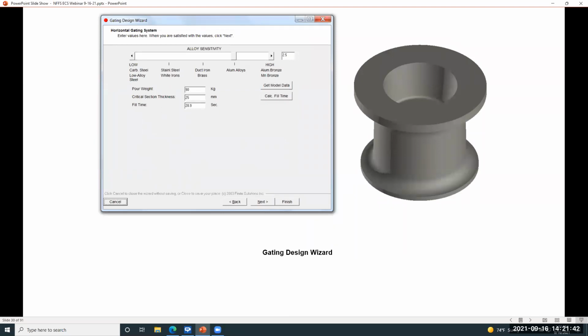In the same way, we can use the gating design wizard, essentially an electronic worksheet where we go through, the system will pull the weight information out of the model. We select the type of alloy we're working with, and we enter what's called the critical section thickness. In other words, the thinnest section that we would need to fill during the filling process, and that would be down on this lower lip here.